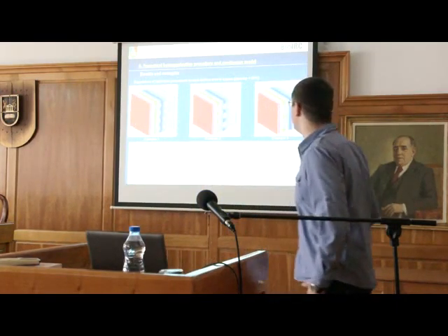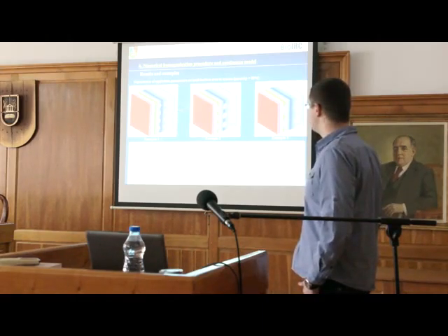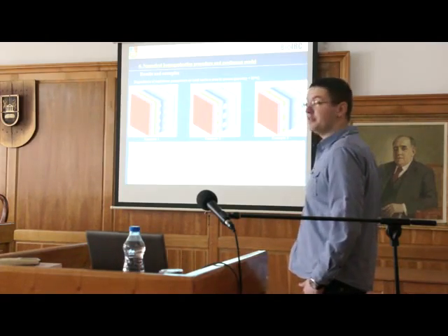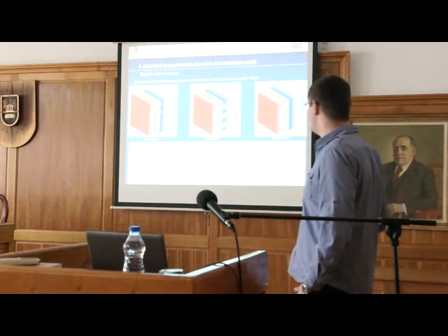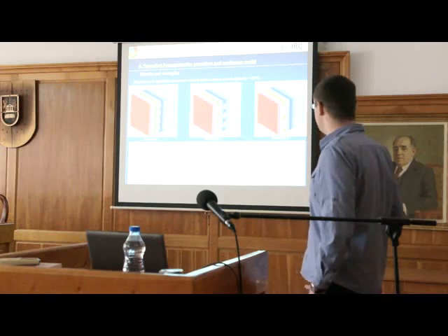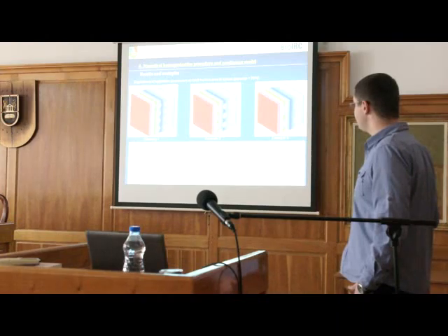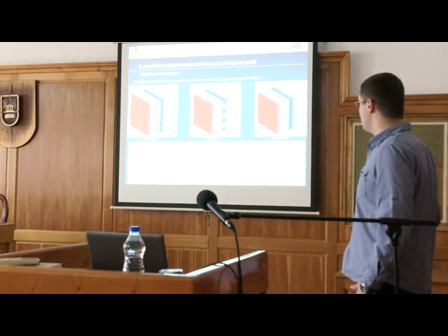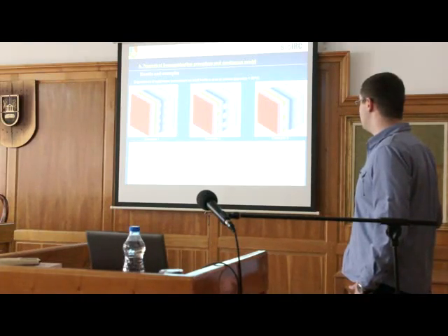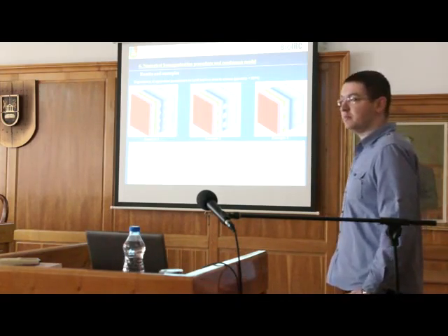We also did some examples with 3 cases. The porosity of fibers is the same for all 3 examples, but the total area of surface in the system is not the same. As you can see, we have different surface areas, and this equivalent distance from the surface is different. For example, for the smallest area, this h is biggest, which means that the diffusion is less constrained.